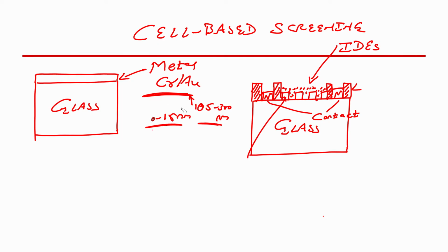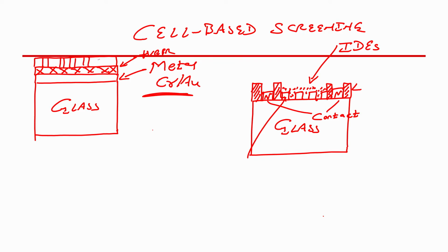So, a thin layer of chrome of 10 to 15 nanometers over which you can deposit gold. After that, the next step would be you will spin coat positive photoresist. Next step, soft bake. Next step, bright field mask. How will the bright field mask look? In the way I want to make the interdigitated electrodes, so easy.